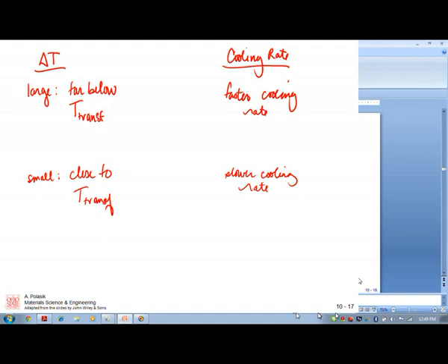So what I would want you to know as far as nucleation and growth is, for which of these delta T's is nucleation easier? Small delta T or large? Nucleation is easier at large delta T. And here growth is easier. And why is growth easier at high temperatures? Diffusion. That's a pretty standard answer. I'll let you know if that changes at any point in this class, but if something's much easier at high temperatures, diffusion is usually going on, that or some kind of chemical reaction.